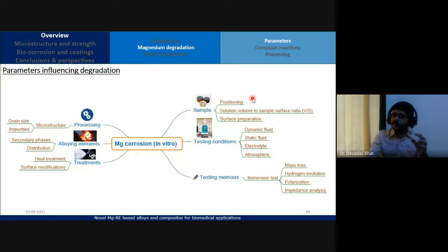So the position of the sample inside the electrolyte is also very important. How frequently you are going to change the electrolyte when you are going to perform the corrosion studies. The size of the sample, and then very important, what we have here is the SV ratio, or the volume to sample surface ratio, right? This is also very important. So all these parameters you will see in the ASTM standard. We follow that and then we perform the test.